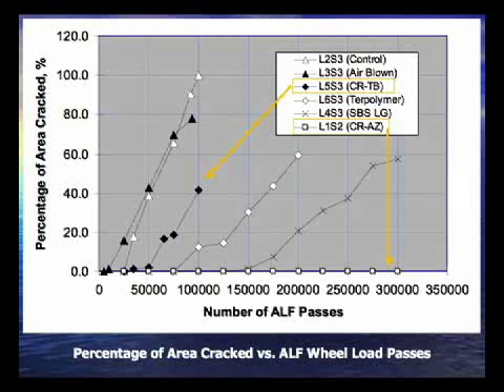And we are in the process of looking at initiation and propagation of these cracks with a portable seismic pavement analyzer and other techniques, because when we do crack mapping, as you can see here, we're only looking at what arrives at the surface. Okay, but what we see here is the percentage of cracked area versus number of ALF passes. This is the composite section with the Arizona wet process. Up to 300,000 passes, we're not seeing any surface cracking. Here, to give you a reference, this is the terminal blend section. In between, we have the terpolymer, the SBS, with the control and the air-blown performing worse, as expected.